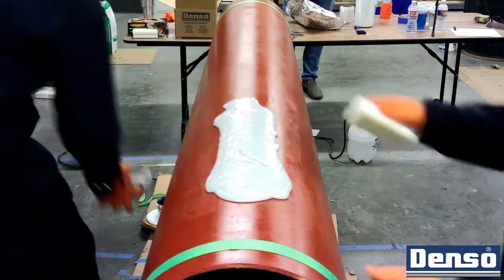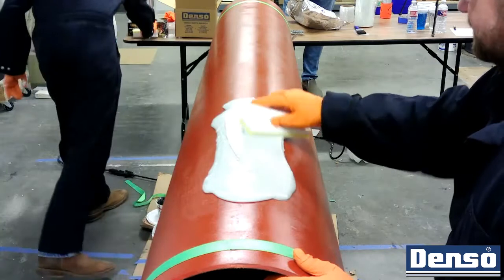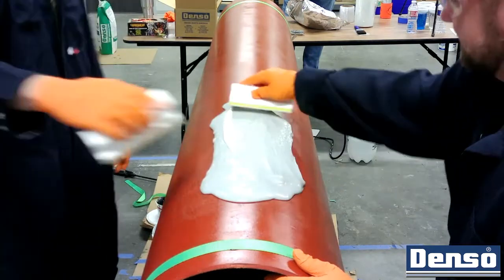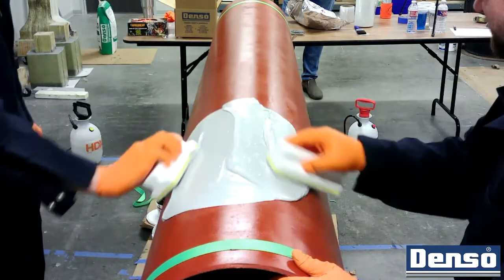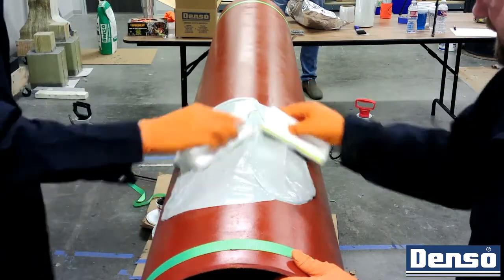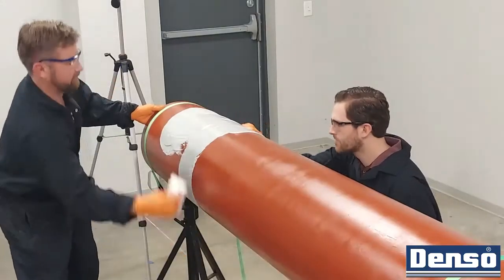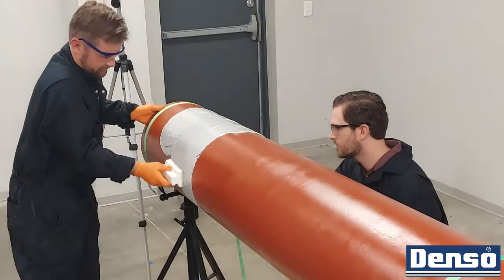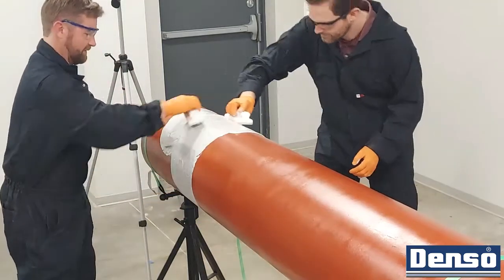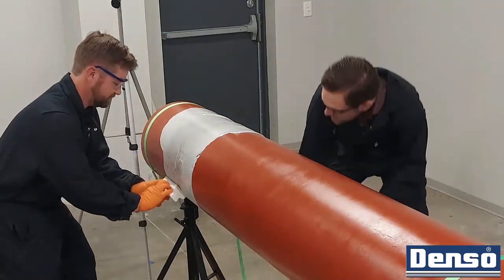Since the full length of the pipe to be protected will not have surface preparation performed, it is key to create a strong anchoring point on the leading section of pipe for the remainder of the bore wrap to tie into. In this instance, we are applying the Denso Protal 7300, which is a moisture-tolerant epoxy.